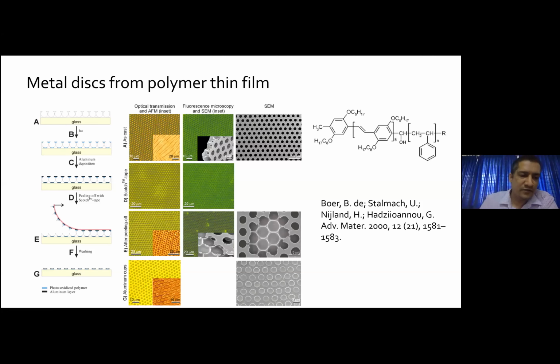And on the scotch tape, you can see that these are all the weak links in the wells, and these are easily broken, and you remove those. Then you wash the polymer. The blue one is the aluminum that is coated, and you can see that you remove the aluminum discs and so on. So the photo-oxidized polymer forms a rigid substrate, and then you coat it with aluminum by a deposition method, and then you peel off, and you generate something called aluminum cups and discs.